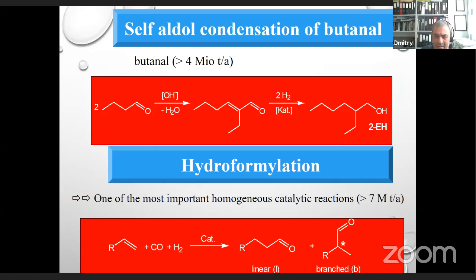homogeneous catalysis by bases, and that's the slide which we didn't see before you. I was going to introduce the self-aldol condensation of butanal, which is once again a multi-million tons per year reaction or process. This is some sort of downstream process of hydroformylation, which is one of the most important homogeneous catalytic reactions itself, where during hydroformylation, olefins react with the syngas, giving a mixture of linear and branched aldehydes, which are then condensed using sodium hydroxide. In fact, the reaction occurs in an aqueous organic mixture.